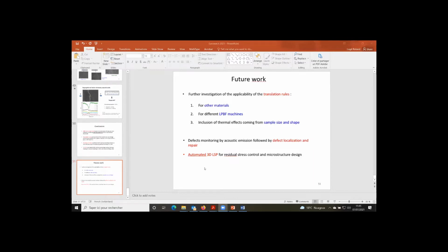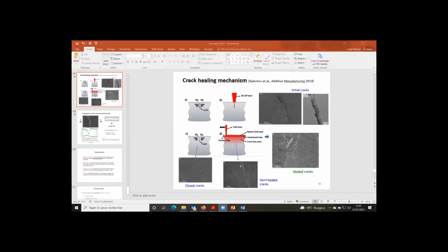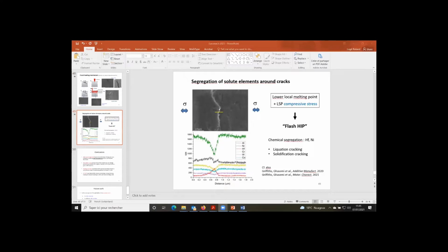Well, actually, if you realize here the temperature that you need to reach, if you remember the simulations from Stephen, you need to reach much higher temperature to be able to locally melt. Here you need to be higher than 800 degrees. So actually, yeah, you would start from 200 instead of room temperature, but also it's usually at the bottom, and it depends on how high you are in the building how effective the heating would be in your sample.